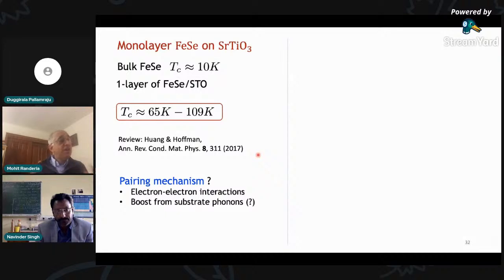So then on to the real world. And again, I don't want to go into the details of the system. Here is a very strange superconductor, a single layer of iron selenide on strontium titanate. Reports range from 65 to 109 Kelvin. And here is a very nice review article. The reason why this is a very strange superconductor is if you make a bulk superconductor, its TC is only 10 Kelvin. But if you make a single monolayer, its TC goes up to 100 Kelvin. It's totally not understood.